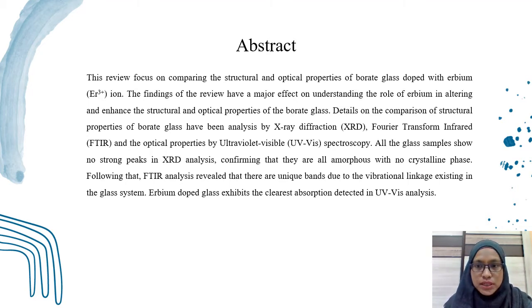Details on the comparison of structural properties of borate glass have been analyzed by XRD, FTIR, and UV-VIS spectroscopy. All the glass samples show no strong peaks in XRD analysis, confirming that they are all amorphous with no crystalline phase. Following that, FTIR analysis revealed unique bands due to the vibrational linkage existing in the glass system. Erbium doped glass exhibits the clearest absorption detected in UV-VIS analysis.